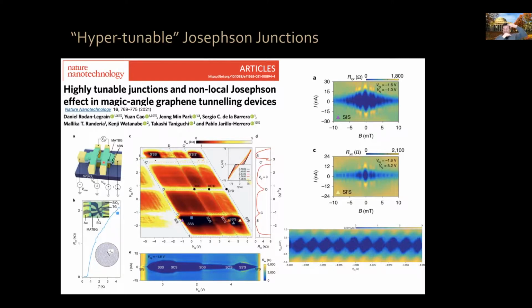The cheese in the sandwich, so to speak, okay? For example, you can make graphene Josephson junctions where the superconductor is fixed, and the graphene you can tune electrically. In magic angle graphene, because we can tune electronically between superconductor, normal metal, and correlated insulator phases, it turns out that by playing with local gates, by putting different metallic electrodes to control the density locally, laterally, we can realize SIS or SNS junctions, okay, Josephson junctions, where both the superconductor and the cheese, the normal piece or the insulator, can be controlled electronically, okay?